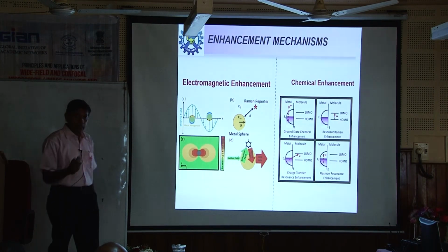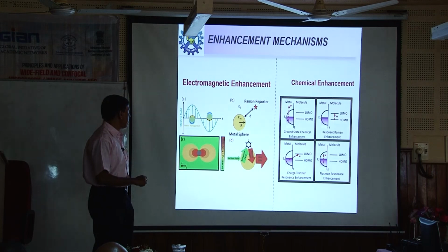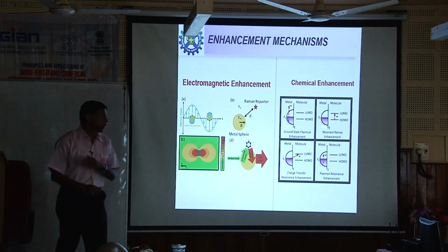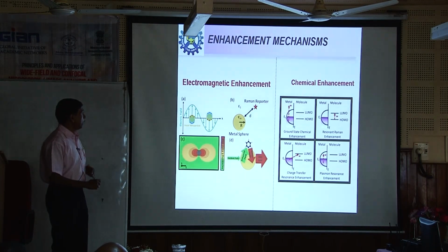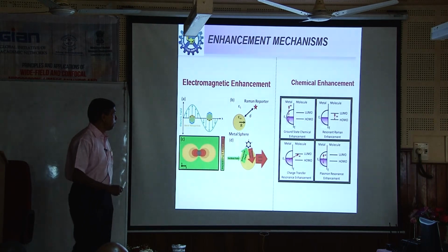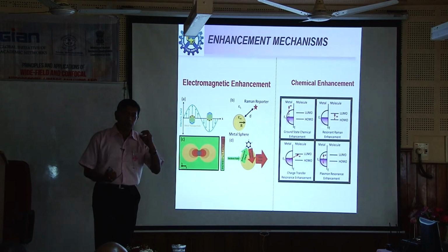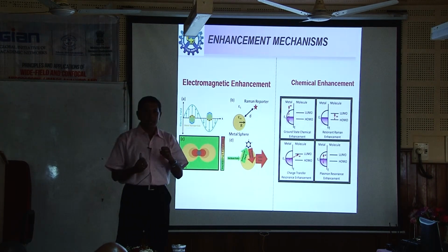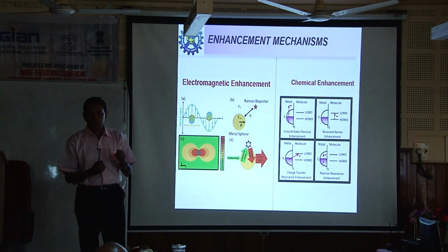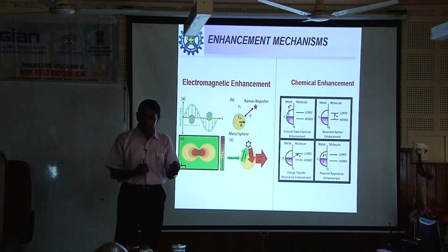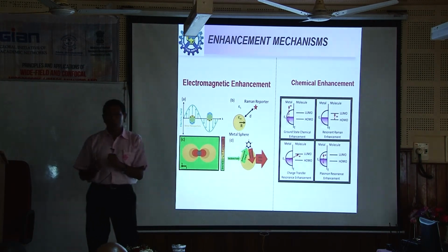So, as I told you, two phenomena are at work. One is the plasmonic phenomenon through electromagnetic enhancement, and that causes the huge enhancement. Another is the chemical enhancement mode, where your analyte molecules may form a covalent or non-covalent bond. If it is a covalent bond, it is called chemisorption, and if it is a non-covalent bond, it is